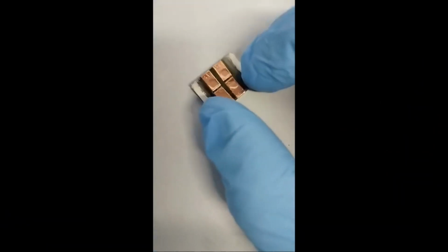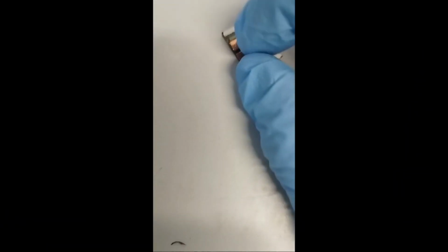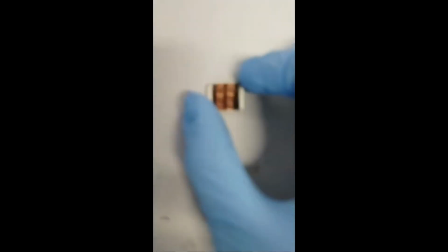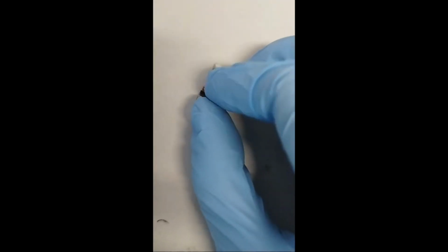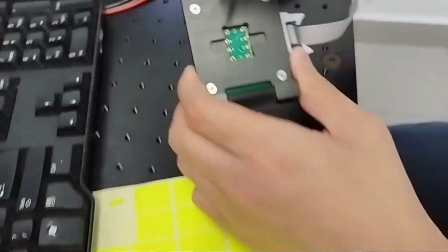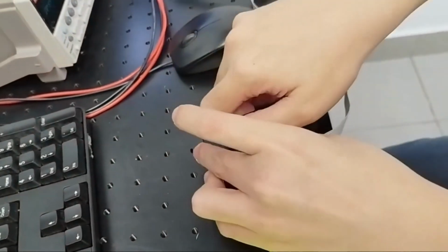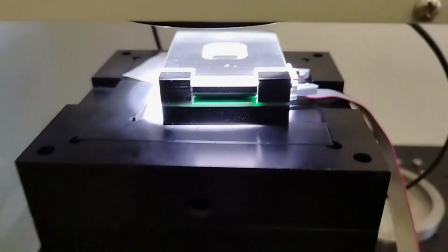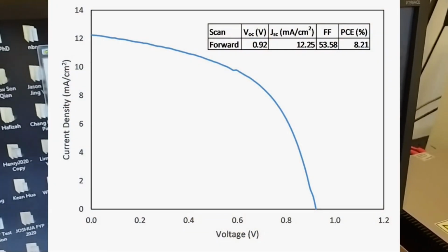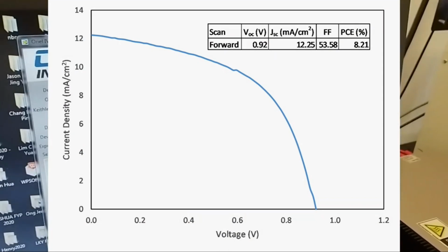As you can see, the carbon electrode is now securely bonded to the perovskite film, and no matter how I try to scratch them, they won't delaminate. With this lamination complete, the perovskite solar cell is now ready for efficiency measurements. The device was able to yield a decent efficiency reading of 8.21% and is expected to show more improvement with further optimization of the hot isostatic pressing process.